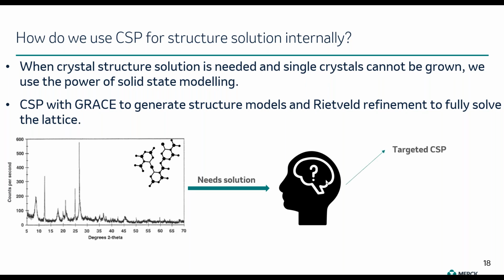How do we proceed? We can do a targeted CSP, so a CSP with a very limited search space, only aimed at solving the crystal structure. We can do an abbreviated CSP, so not delimited severely just to solve a crystal structure, but also not a full-blown one like you do for a candidate drug. So for example, you can limit the Z prime, or you can just consider certain space groups. And finally, one could also go into a full-blown CSP, generate all structural models, and then perform the refinement and the structural solution at a later stage.